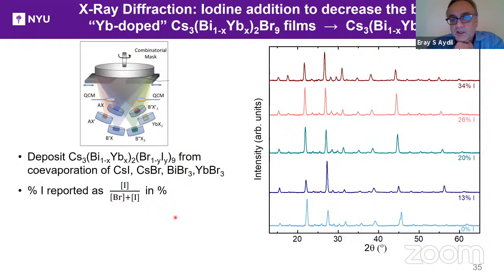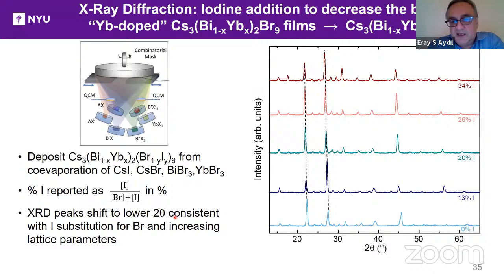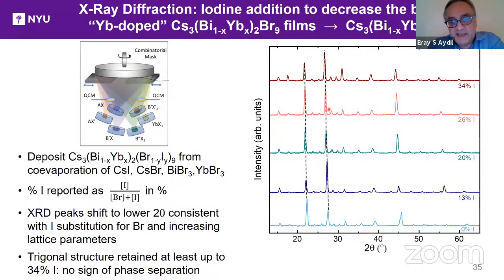So we did that. So now we have four precursors: cesium iodide, cesium bromide, bismuth bromide, and ytterbium bromide. And we went from zero to 34% iodine in the bromine positions. And X-ray diffraction shows that iodine is substituted. We don't see any sign of phase separation. I don't know if you can see, but those dashed lines are actually sloped. So the peak is actually shifting to lower two theta because iodine is bigger and the unit cell is expanding. So the trigonal structure is retained at least up to 34% with no sign of phase separation.